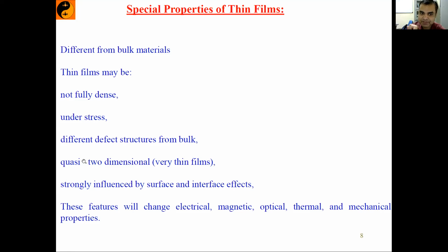Similarly, these thin films are quasi two-dimensional. They are very thin films, and they are strongly influenced by the surface and the interface effects. Interface effect, I have already discussed: since you are integrating with respect to the substrate, the substrate tries to invoke its own force on the unit cell of the evaporants of the thin film. So that is why the interface actually controls many of the properties.